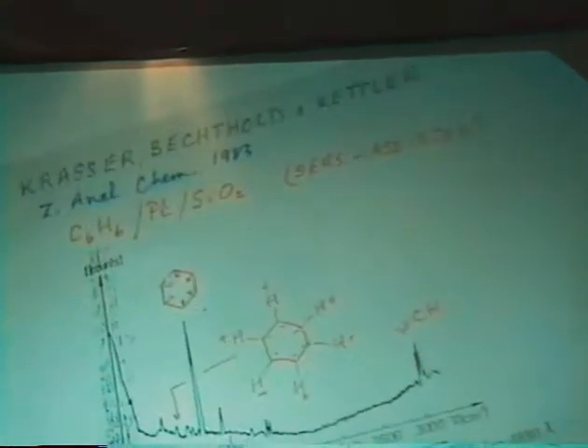Well, one can sometimes get spectra from hydrocarbons by Raman spectroscopy. It's difficult, and probably there's a degree of enhancement here, but those are some spectra that Krasser and colleagues got from benzene on a finely divided platinum silica catalyst. And of course, if you have rough surfaces with surface-enhanced Raman spectroscopy, you can get beautiful spectra. But the problem here is, as Martin Moskovits has recently shown, that probably this technique brings up one species but doesn't see others that are present. Nevertheless, it gives you beautiful spectra.